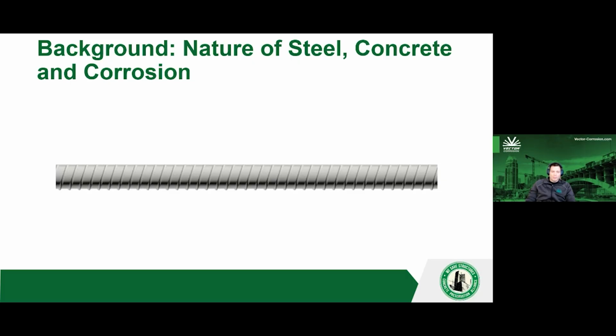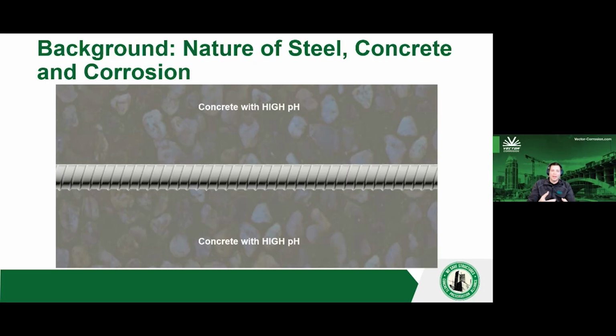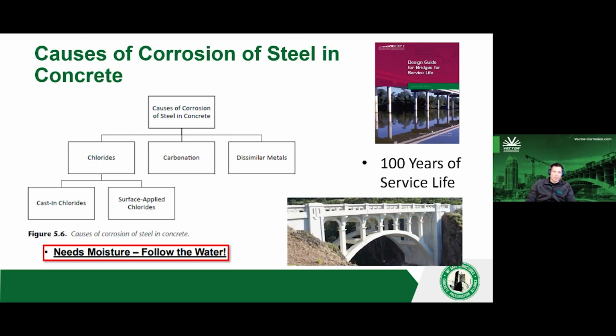So you might be asking yourself, why on earth would you put this piece of reinforcing that wants to corrode, and when it corrodes, it expands into concrete, which cannot take that expansion? Fortunately, good quality concrete has a high pH, and it creates an environment that helps steel hold its energy. I'm not going to get deep into the chemistry here, but just know it creates something called a passivation layer. It's like a little cocoon that keeps the energy in the steel and stops it from corroding. Very, very durable combination, steel and concrete, and that's why it's very widely used in construction. So the problems really take place when you have that passivation layer break down.